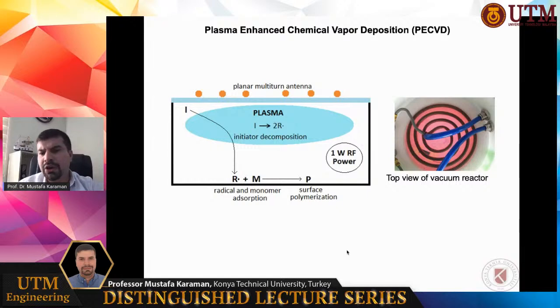Here you can see on the right-hand side the top view of one of our PECVD systems. You can see the discharge glowing in bright pink color. This is a monomer discharge, and a substrate is placed in the bottom of the reactor. The reactor top is covered by a thick quartz glass so that we can have visual access to the substrate surface. The copper antenna is placed at the top, and that copper antenna is connected to a plasma generator. We apply 13.56 megahertz plasma power to the antenna, which helps to discharge the bright plasma. And then after the initial discharge, the fast deposition rate starts. You can see on the left the schematic representation of the system.